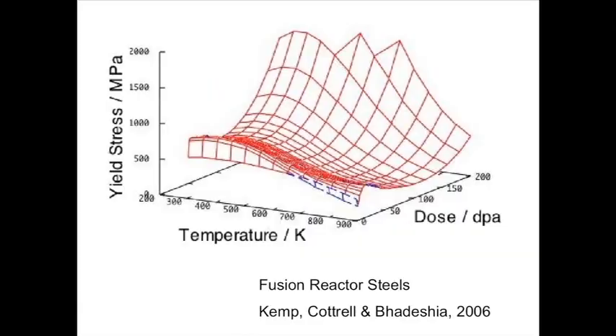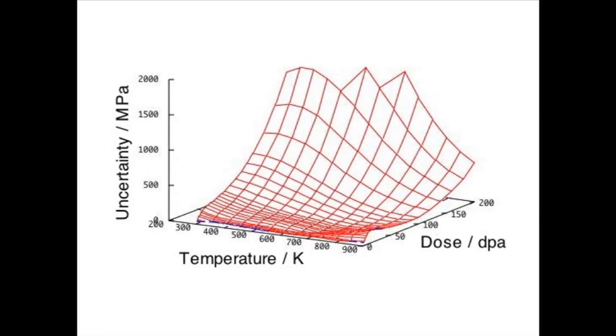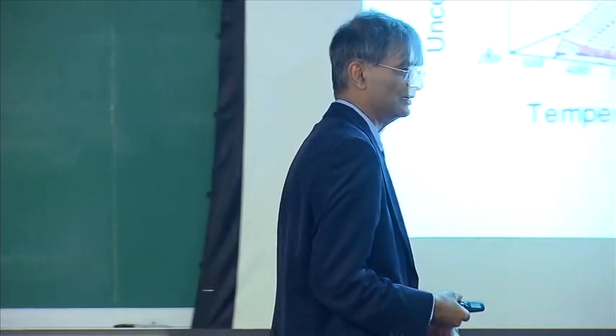So the idea is we want to do experiments in regions where data do not exist, okay, because there's a limited amount of volume that will be available. So we worked on this, and here I'm plotting the yield strength increase as a function of the displacements per atom and as a function of temperature. And you can see that irradiation would produce a huge amount of hardening, which will cause problems with toughness. But the more interesting part is to look at the uncertainty. Okay? So this uncertainty defines where we need to do experiments. Okay? So the purpose is not really to predict the hardening, but to predict the regions of that complicated input space of 36 variables where experiments are necessary. We don't need to do experiments in this region where the uncertainty is small. Okay? So we are using this in order to define where the experiments are necessary.